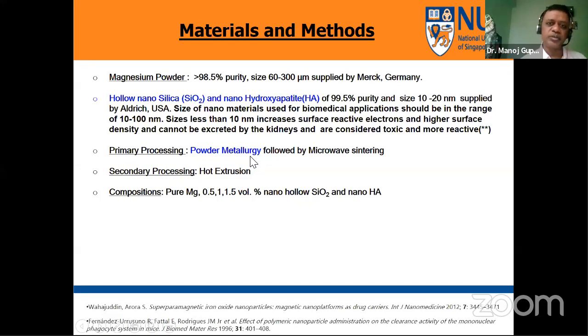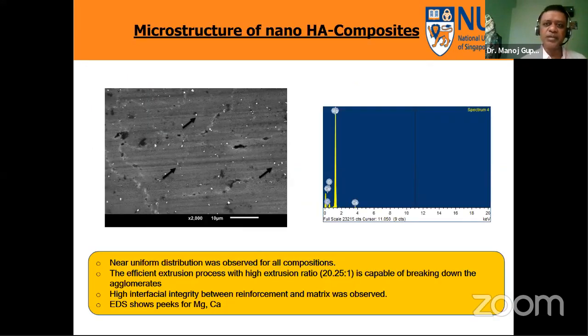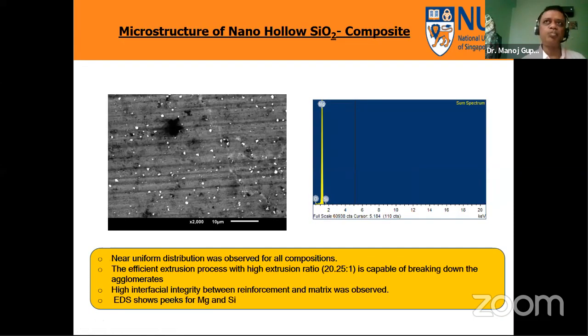We put this material through hot extrusion and tried 0.5, 1, and 1.5 volume percentage of reinforcement. What you see in this picture is quite a uniform distribution of the hydroxyapatite particles, confirmed by EDS analysis, showing that our processing technique gives a uniform distribution. Note that with uniform distribution, we want uniform properties and uniform corrosion response.